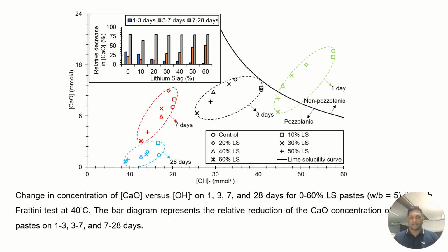Therefore, the Frattini test fails to characterize high volume pozzolan cement composites. However, the test continued to understand the relative decrease of calcium concentration, as shown in the top left. This was very helpful in the characterization of the activation time for the lithium slag mixes.